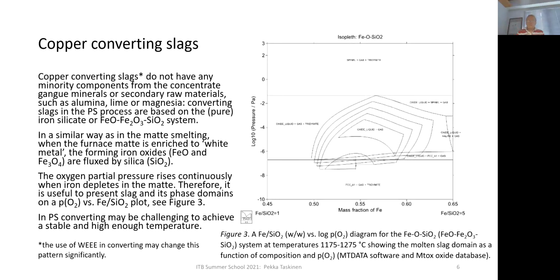So in this sense, copper converting slags are a simplified version of copper smelting slags, and this is why the issue of slags is not as important in the converting step as it is in the smelting step. But what is important is that because you are adding cold sand into the converter, there may be difficulties in the first minutes or tens of minutes of copper blow and slag blow to maintain correct temperature for the slag.